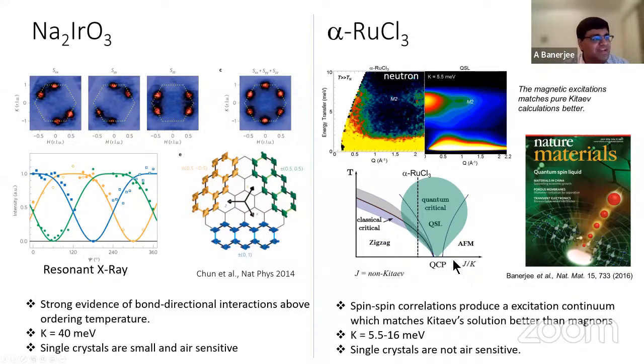So if you look at the phase diagram, at low energies and low temperatures, you basically get remnants of an antiferromagnetic state, but it is very close to a Kitaev spin liquid state, as if you can just take this line and move it a little bit, and you will go right into the Kitaev spin liquid state. But lo and behold, at higher temperatures and at higher energies, you still get a part of the quantum critical fan. You get access to some of the quantum critical states that you would get from a quantum spin liquid.